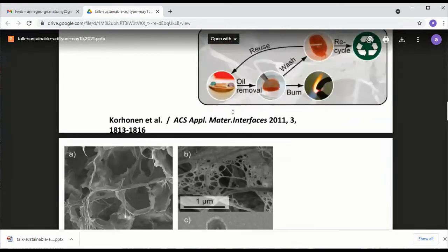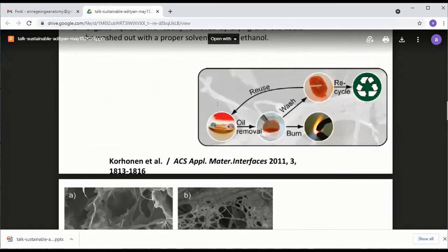Once you do that, look at this picture. You sprinkle this nanocellulose aerogel in seawater. The red is oil. All the oil is absorbed by this aerogel, which is hydrophobic. Oil is hydrophobic. And this aerogel cannot take water because it is hydrophobic. And you collect all the oil and collect all this aerogel. You can squeeze out and reuse the oil, or you can burn the oil. So they have scaled up this technology for removing oil from water.